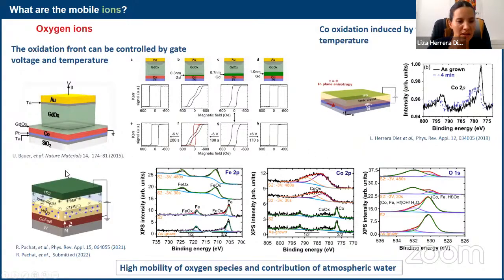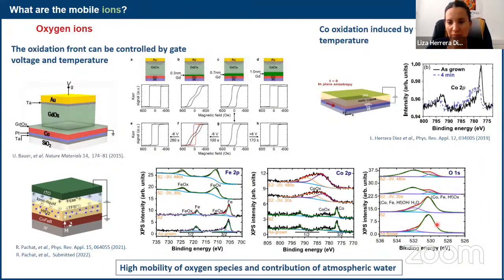And then I will show you later on that we did similar experiments with cobalt, iron, boron. And once again, we could see by XPS how the iron and the cobalt was evolving into an oxidized state. And not only that, but also we could measure the oxygen, where we could see that there was an additional oxygen peak. Let me see if I can show you the pointer. So here we have a big oxygen peak at the beginning on the as-grown sample, and then when we apply electric fields, we see that there is a second peak that is really growing a lot, and this is oxygen that was introduced in the system with gating. So we could see that there was another type of oxygen that was growing because of the gating. So once again, showing that some oxygen activity was happening in the system.